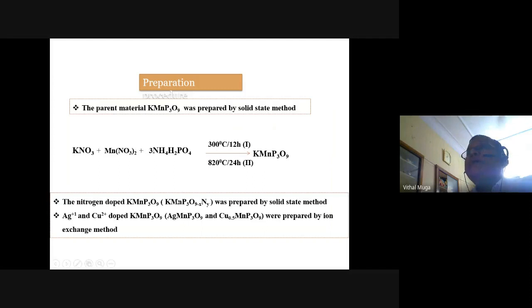Now, how did we prepare this? This is a very simple method of preparation: potassium nitrate, manganese nitrate, ammonium dihydrogen phosphate. Thoroughly grind it and then heat it at 300 for 12 hours and then cool it, and once again grind it and heat it at 820 for 24 hours. You will get the material.